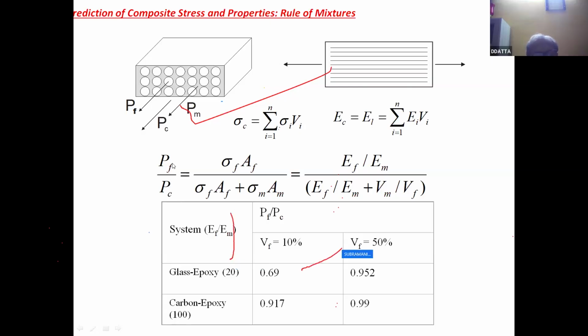What is important is that this relation P_f by P_c, that is sigma_f A_f by sigma_c A_c, can be manipulated to this expression. Now, if we use a system made of glass fiber epoxy, which we have discussed, and the volume fraction is 10%, then for this glass epoxy the P_f by P_c ratio is 0.69. That means 69% of the load is carried by the fiber, where the fiber presence is very small, merely 10%. Whereas if it is 50%, then 95% of the load is carried by the fiber.